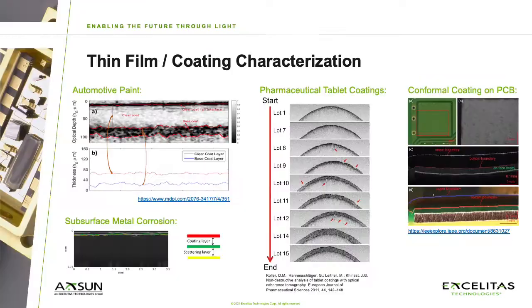OCT's cross-sectioning ability makes it a promising tool to perform 100% inspection on thin films and coatings as an alternative to random and destructive point sampling. Some examples shown here include automotive paint or the conformal coatings used to protect printed circuit boards. In these applications, the thickness and continuity of the coating is often critical for longevity, and surface defects can shorten the time to failure. OCT can even detect metal corrosion below the surface of a coating.